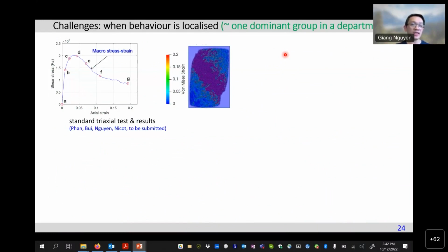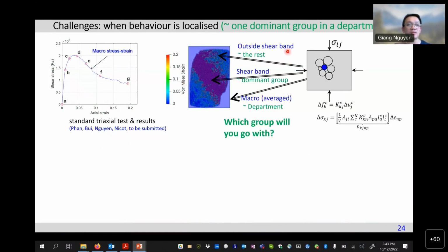But if we look at the test, as you can see here, is our test run by one of our postdocs at Monash with Professor Ha Bui. And you can see here the behavior in this case is localized on a thin, narrow zone here. It's like we have in a department a big dominant group that performs much better than the rest. Okay, so I conceptualize this like this.